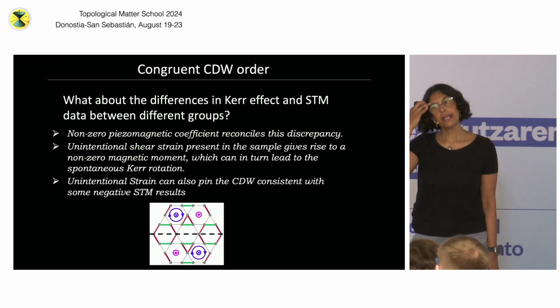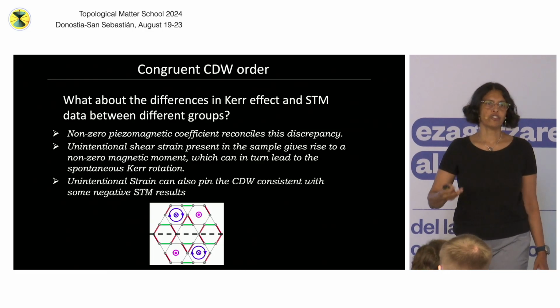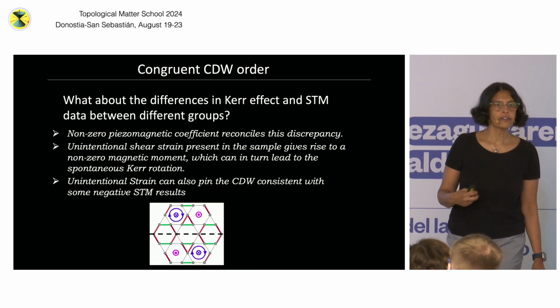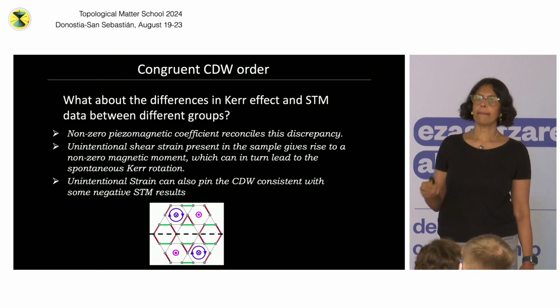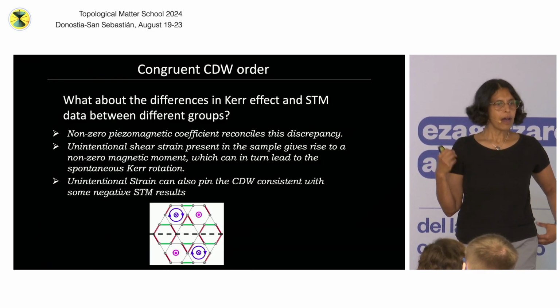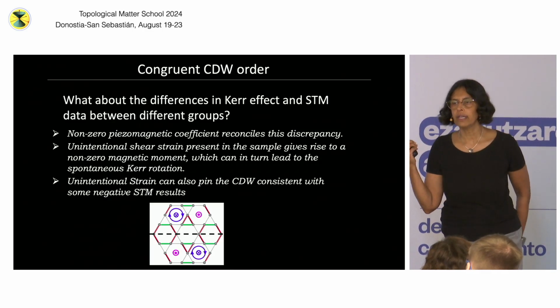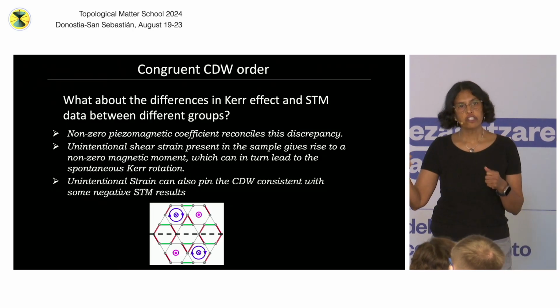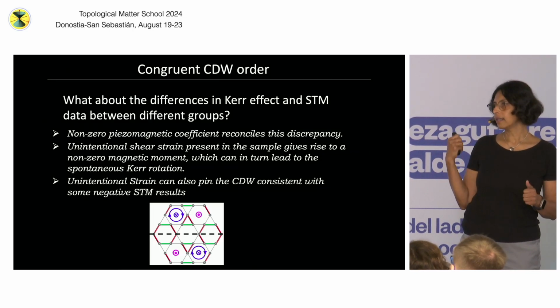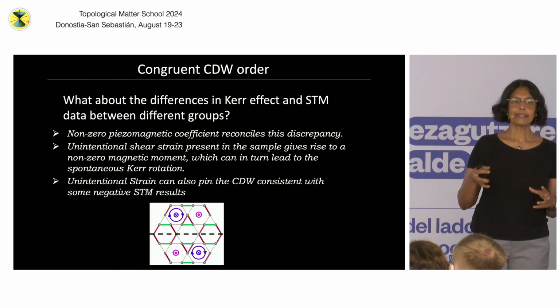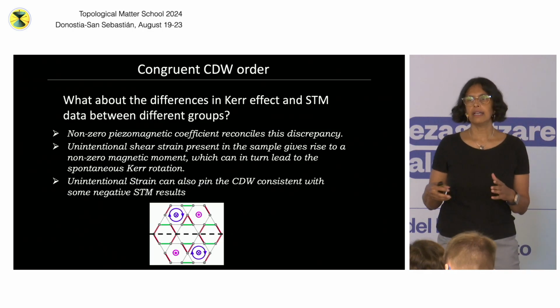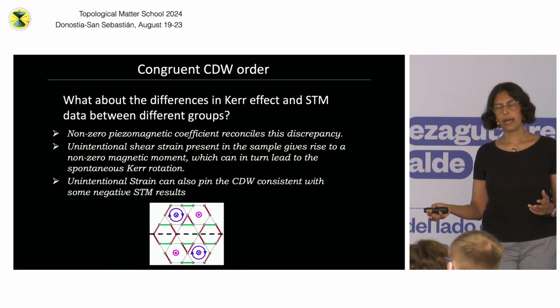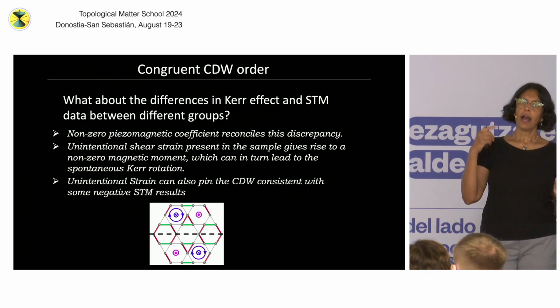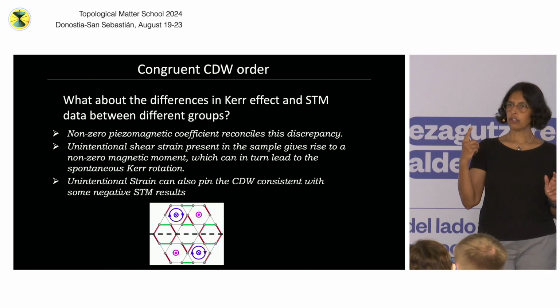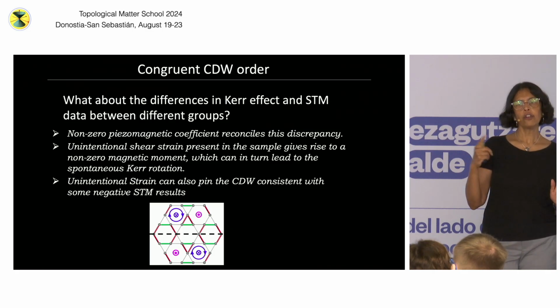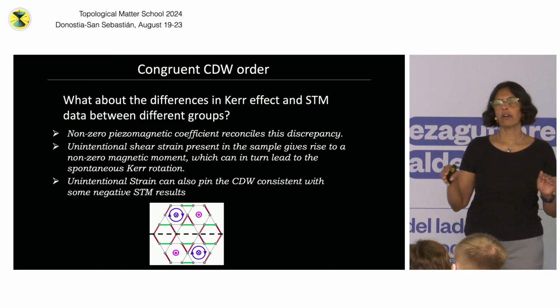Essentially, what we believe is happening is that all the experiments are measuring real things. The controversy arises because of the differences in the amount of strain in the sample. From our experiments with the magnetic field, we can see that in this system, if you have shear strain, you'll get a net moment, okay? That can explain why different Kerr effect data see either broken time reversal or no broken time reversal. If you had no strain, the kind of order that we are talking about with the loop currents will not give you a Kerr effect. So there should be no Kerr effect.